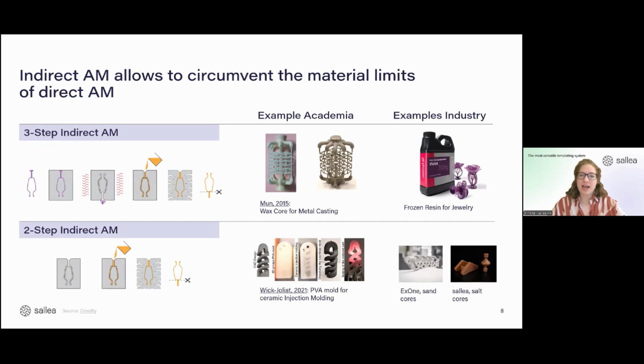Now, of course, over time, this has also evolved, and basically two-step indirect additive manufacturing has been established. And here, instead of having that extra step of first printing something to even make the mold, you directly print the mold. But that means that it needs to be also water soluble. And this is exactly what we also do at Sallea.